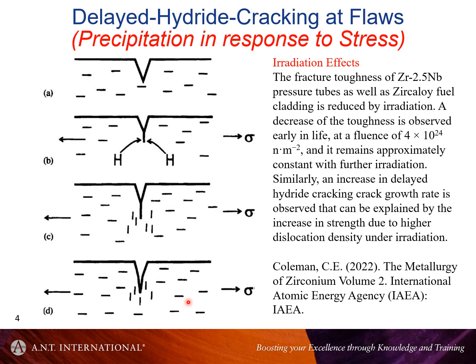Again, lots of models to apply here, but suffice to say that once the hydride gets to a certain size, it breaks. I don't know what the reason is, but you just have to know empirically that the hydride will break once it reaches a certain size. It cracks in a brittle manner, and then the crack advances, and the hydriding process can start again.